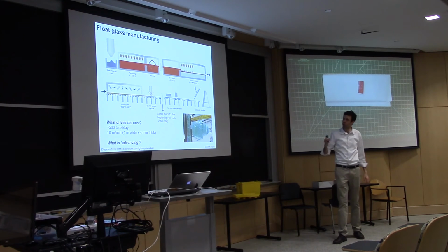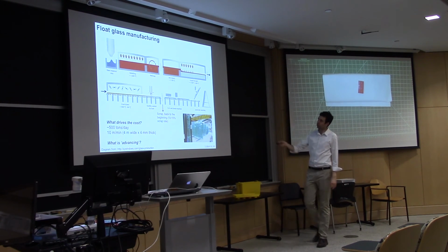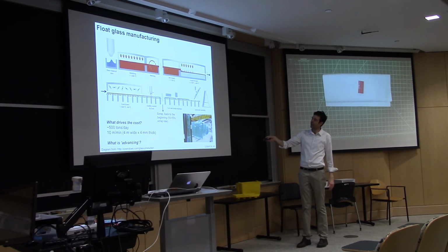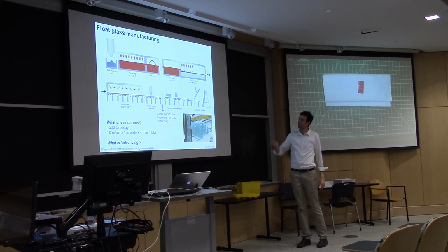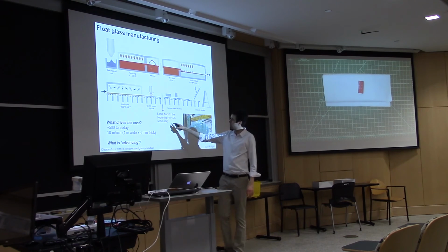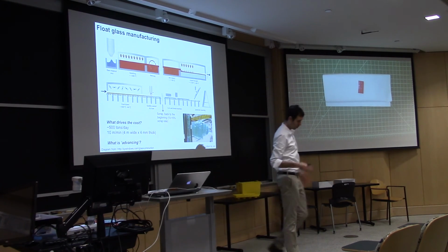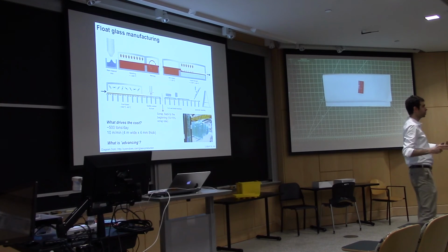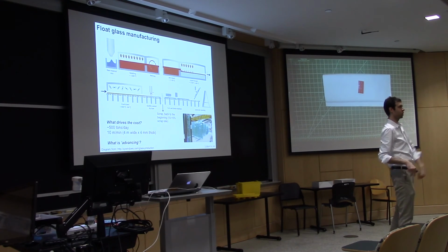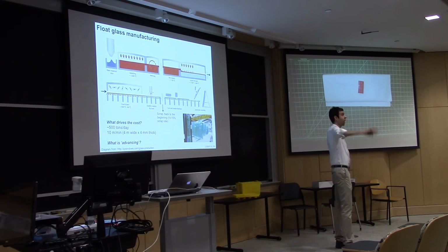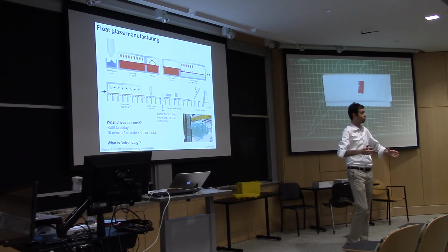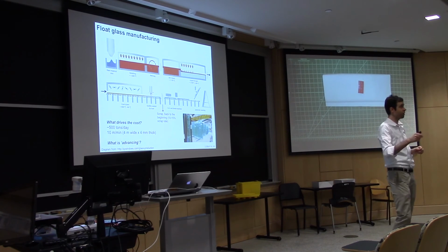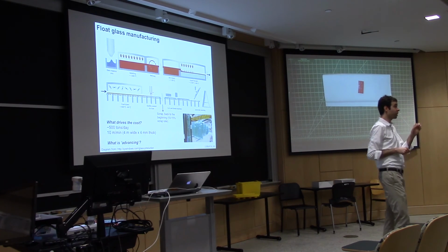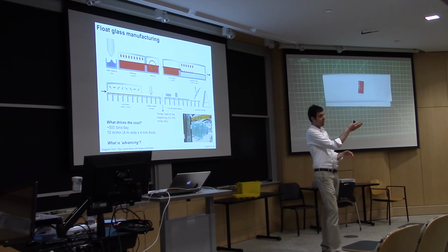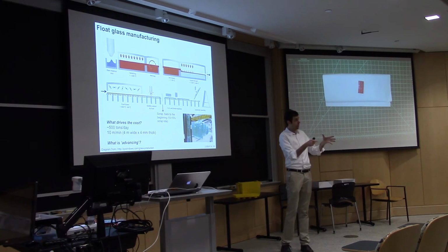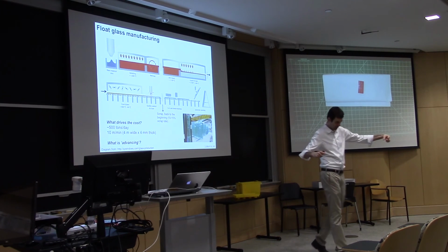And a couple more interesting things. One is, when I said they have a laser inspection, and then they cut the glass into pieces, they had a defect specification. They said, well, on a particular day or a particular week, we're making glass for a certain customer, like we're making it for Ford, or for shower doors or something. And each customer or type of glass had a thickness specification and a defect specification. Like you couldn't have a void in the glass that was bigger than like 0.1 millimeters. And they had laser inspection equipment that would determine whether a certain pane of glass met the spec.